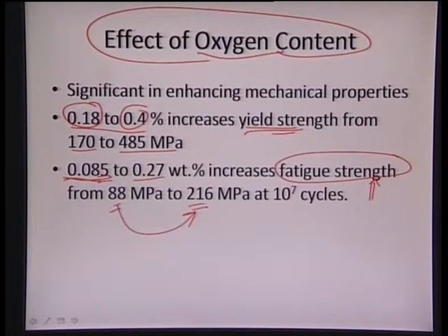So we can realize that higher oxygen content is very useful in terms of increasing the yield strength, and at the same time increasing the fatigue strength, because those sites act as some high energy regimes, and it becomes difficult for the slip to occur, and that basically provides an increase in the yield strength or the fatigue strength of the particular titanium alloy.